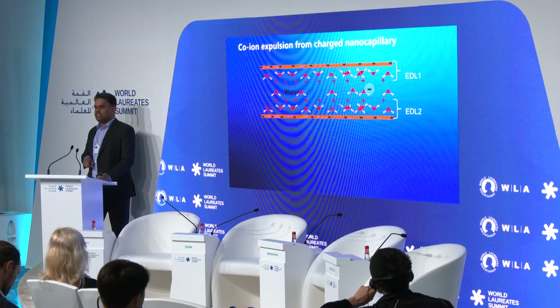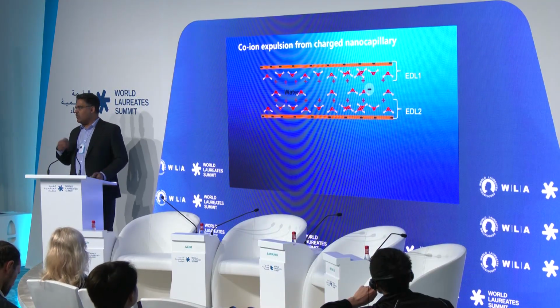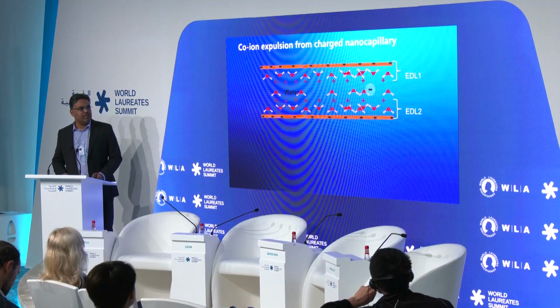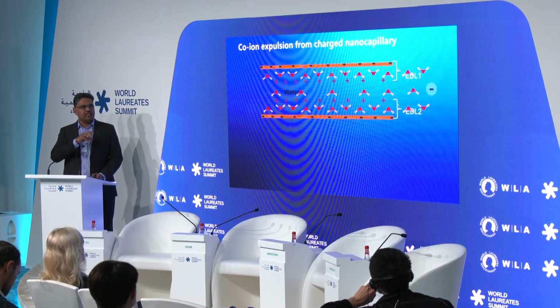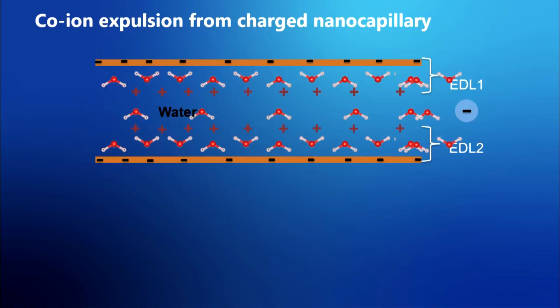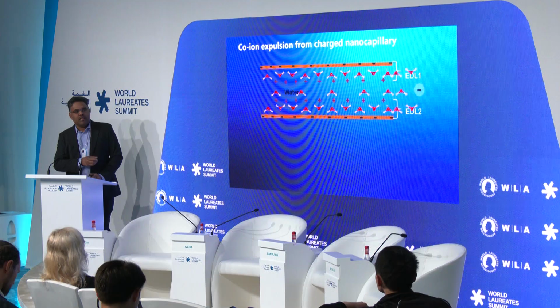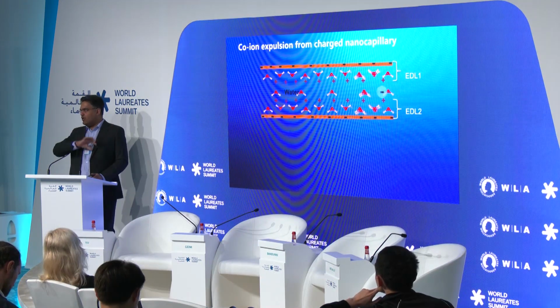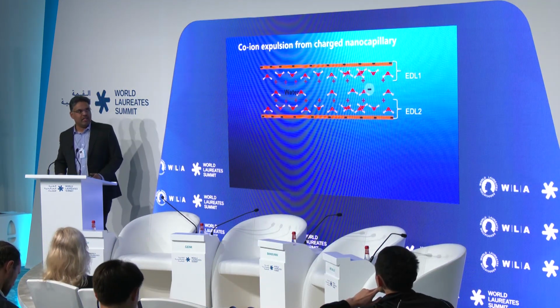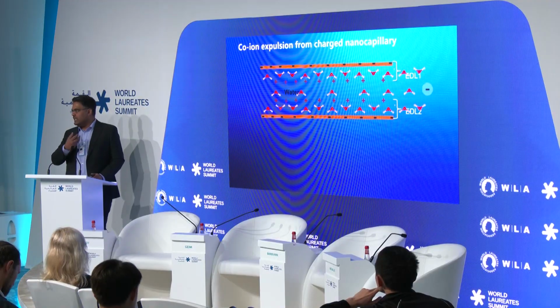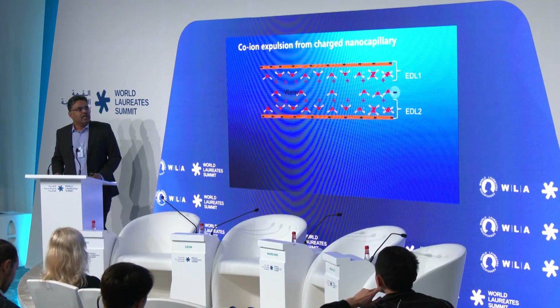Now we think a little bit differently. We think, okay, can we somehow create this ion, a negative co-ion, inside a negatively charged capillary? If that is the case, these ions are not stable because of the electrostatic repulsion, they should come out from the channel immediately. And if ions are coming out, that creates an osmotic pressure, and the ion also will drag the water out of the channel, and that is a possibility of taking water out from such a capillary.